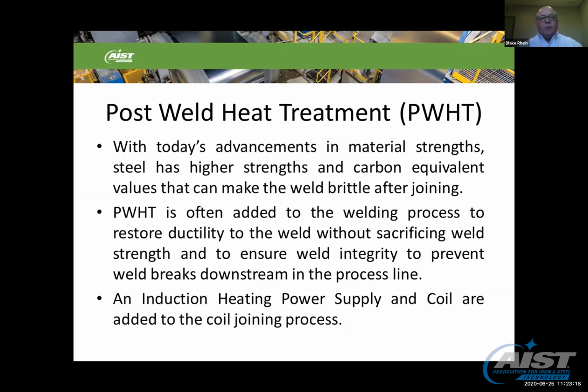My last couple slides will talk about today's strip material and what's called post-weld heat treatment. With today's advancements in material strengths, steel has higher strengths and carbon equivalent values that can make the weld brittle after joining. Post-weld heat treatment is often added to the welding process to restore ductility to the weld without sacrificing weld strength, and to ensure weld integrity to prevent weld breaks downstream in the process line.